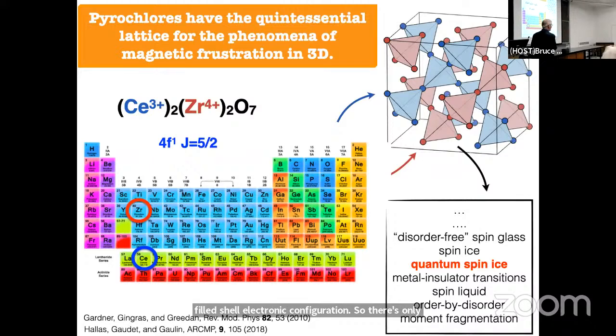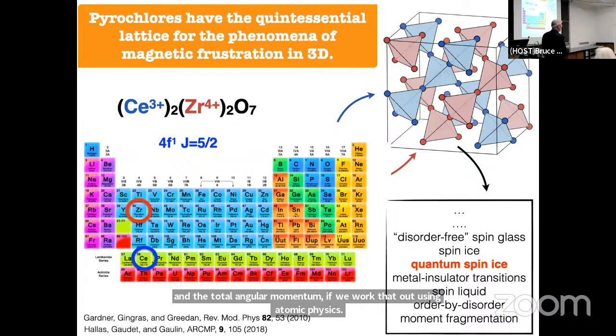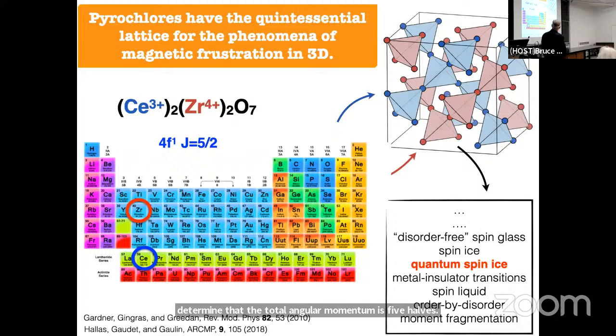The only degrees of freedom are associated with the cerium 3+, and 3+ means that we have 1 electron in the 4f shell. Okay. And so there is a partially filled orbital here. It's the 4f orbital. And if we apply Hund's rules to work out the total spin angular momentum, the total orbital angular momentum, and the total angular momentum, right? If we work that out using atomic physics, we'll determine that the total angular momentum is 5/2. That's associated with the ground state of cerium 3+.